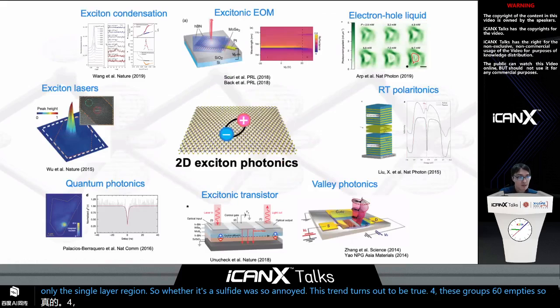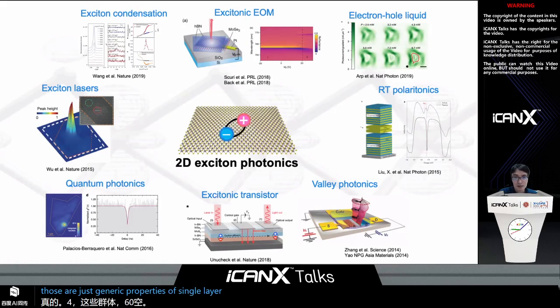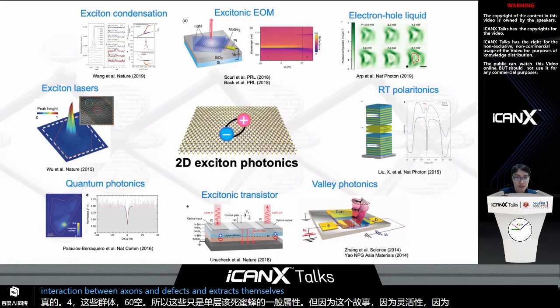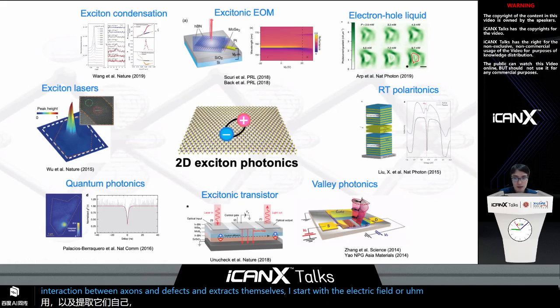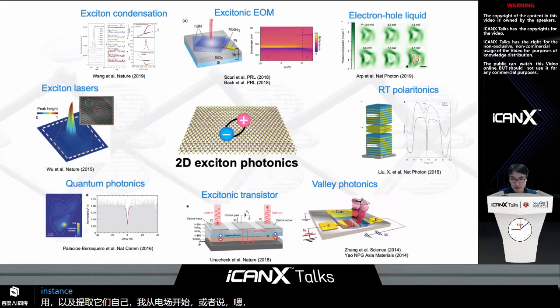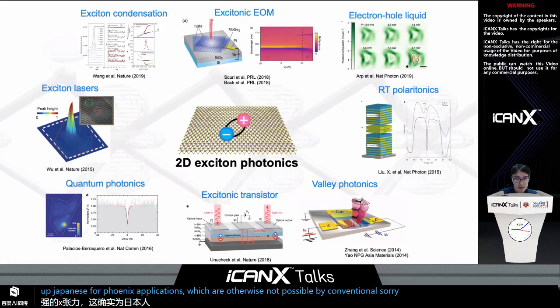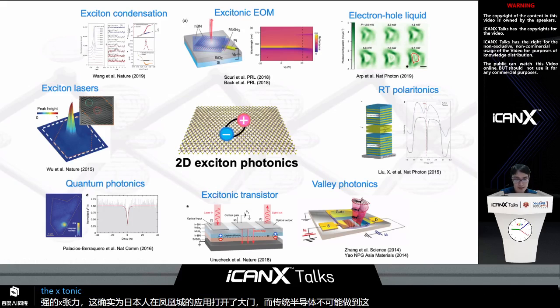So those are just generic properties of single layer TMDs, but because of the symmetry, the flexibility, and the strong interaction between excitons and defects, excitons themselves, excitons with electric field or external particles, for instance photons, the strongly excitonic nature of 2D semiconductors really opens up avenues for novel photonics applications, which are otherwise not possible with conventional semiconductors like gallium arsenide, where the excitonic properties only kick in at very low temperatures.